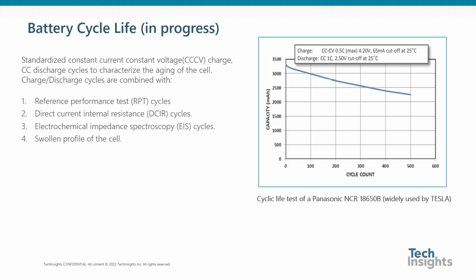Battery cycle life is one of our in-progress subscriptions aiming at characterization of batteries over cycling. It includes standardized CCCV charge, CC discharge cycles coupled with reference performance tests, direct current internal resistance measurement, and electrochemical impedance spectroscopy. The standardized CCCV charge and discharge cycles are adopted from the standard device operation.